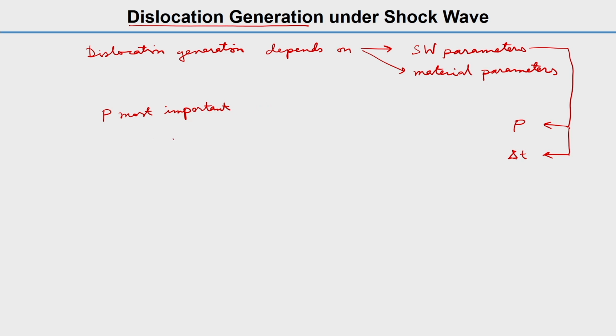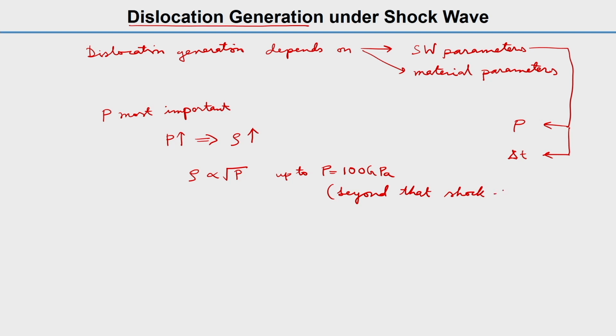What happens is, when pressure increases, the dislocation density rho will also increase. Generally, rho is proportional to the square root of P, the pressure, at least up to 100 gigapascal pressure. Beyond that, shock induced heating will affect it.